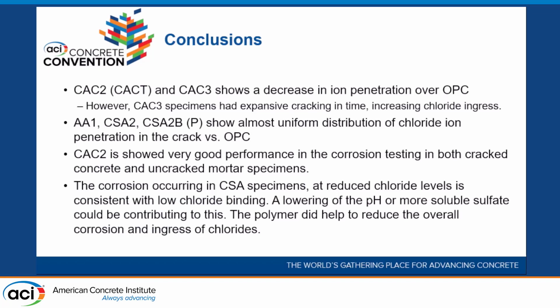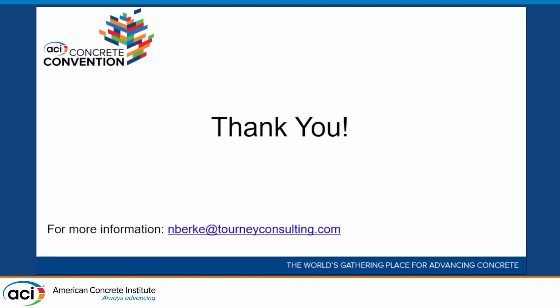And basically the corrosion occurring in CSA specimens occurred at reduced chloride levels, consistent with low chloride binding, and a lowering of pH or more soluble sulfate could potentially be present, contributing to this. The polymer did help to reduce the overall corrosion and ingress of chlorides.